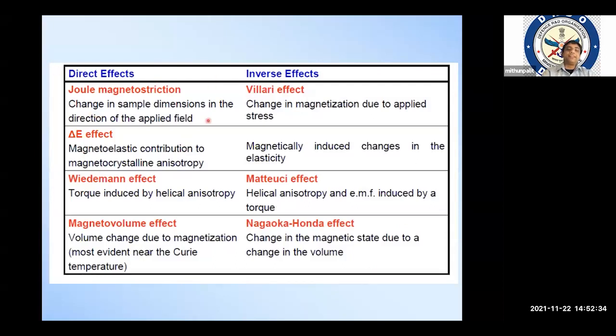Direct effects are Joule magnetostriction, which I described, the delta E effect, where a change in the elastic modulus under the magnetic field is observed, the Wiedemann effect, where the material produces a torque and gets twisted under the influence of a magnetic field, and the magneto-volume effect. In the Joule magnetostriction case, under the magnetic field, the volume remains constant. So if the length increases, the diameter decreases. Whereas in the case of the magneto-volume effect, there is an overall change in the volume under the influence of an external magnetic field. The inverse of the Joule effect is called the Villari effect, the inverse of the Wiedemann effect is the Matteucci effect, and the inverse of the magneto-volume effect is called the Nagaoka-Honda effect.